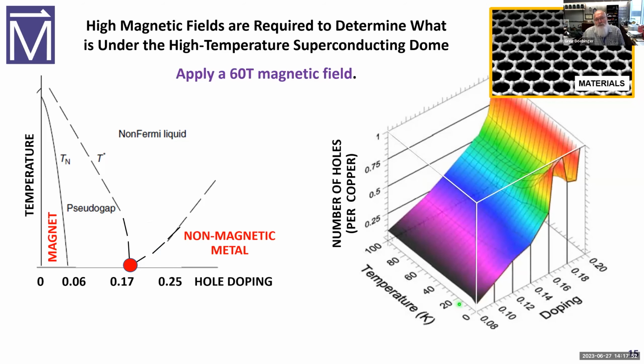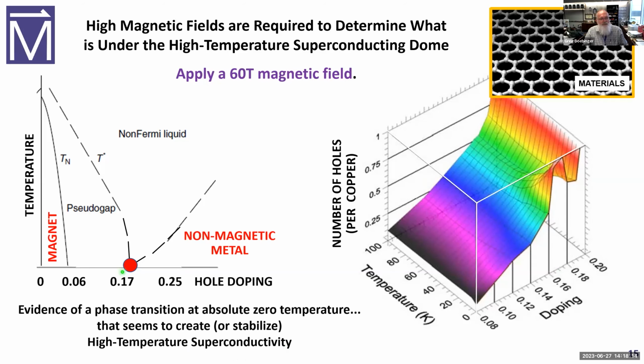So with a magnetic field of 60 Teslas, you can remove that superconducting dome and see that underneath you get this peak in the number of mobile carriers that occurs right at the same 0.17 doping where superconductivity is optimized. So you get the ability to see what's happening at low temperatures. And this is evidence of a phase transition at absolute zero temperature that seems to somehow create or stabilize high temperature superconductivity. It occurs at the same doping where in the resistive state, where the material is the best at being a superconductor. So either nature is telling us that these two things are linked, or nature is being incredibly cruel and misleading us.